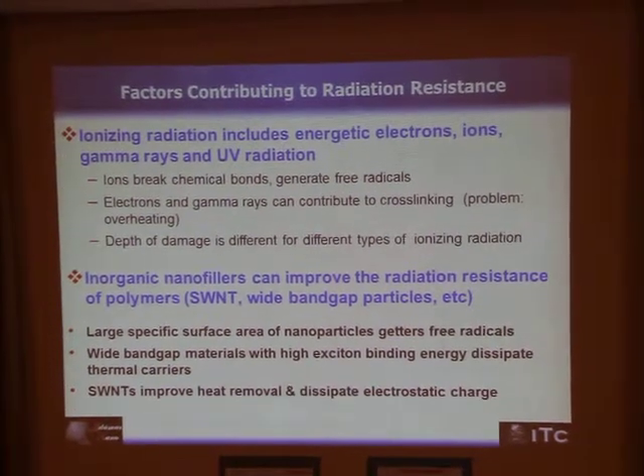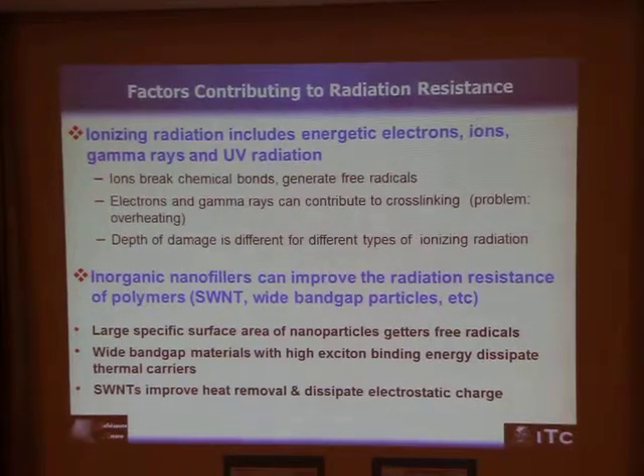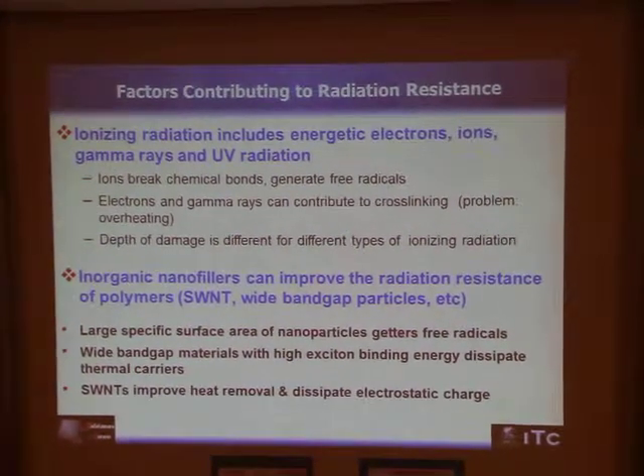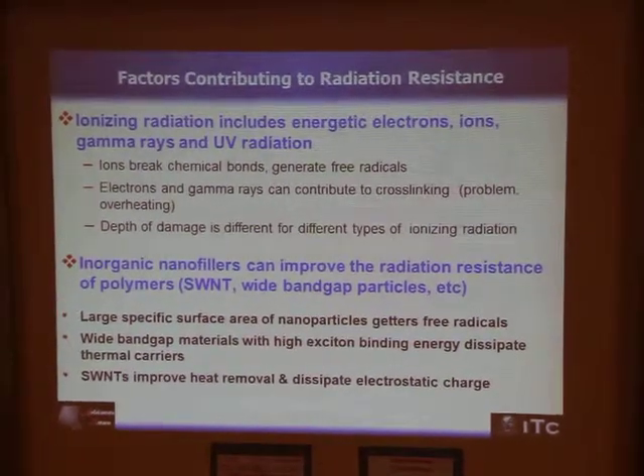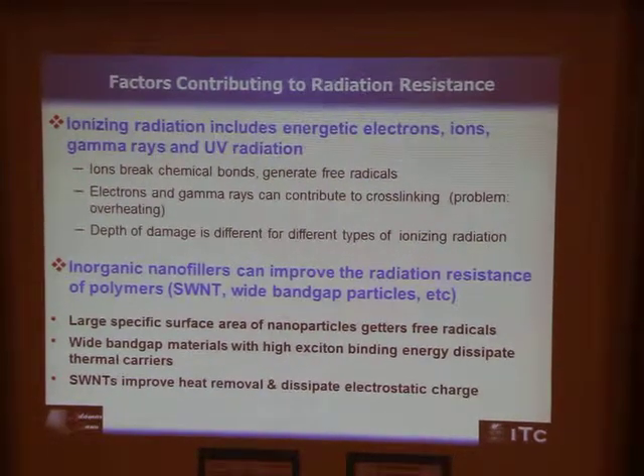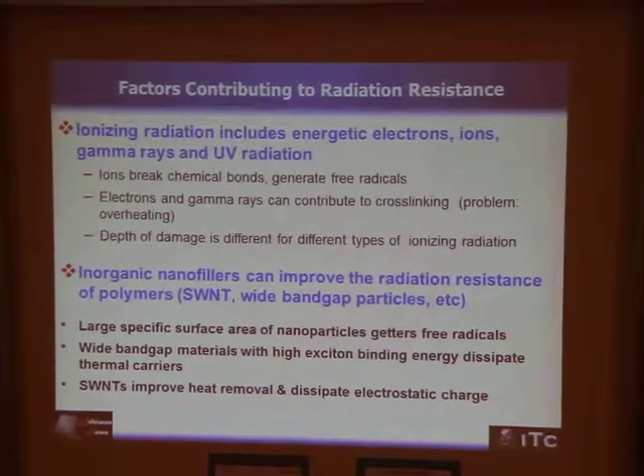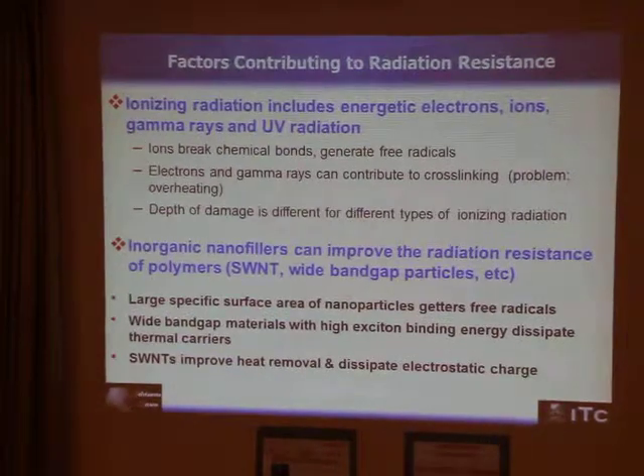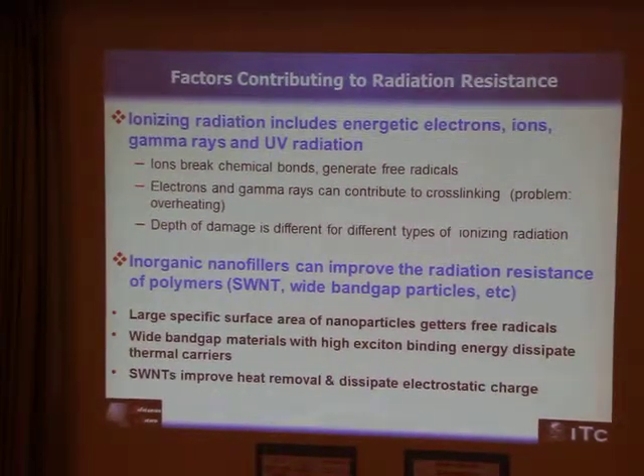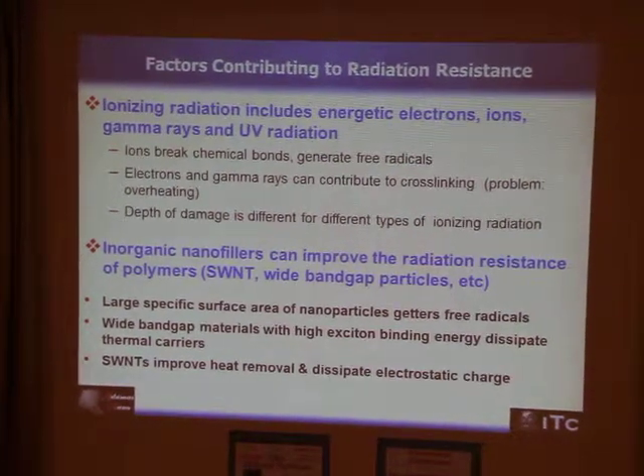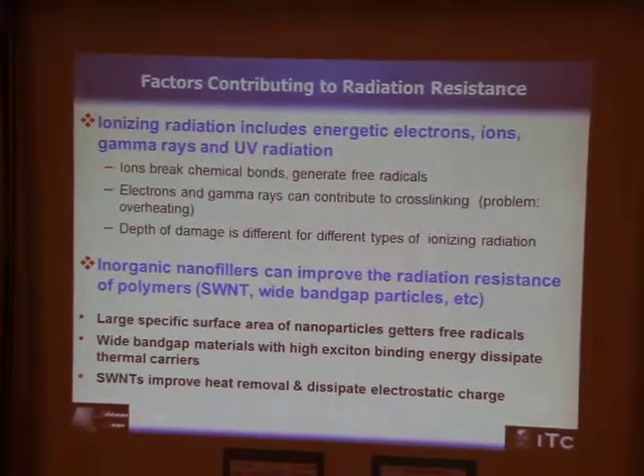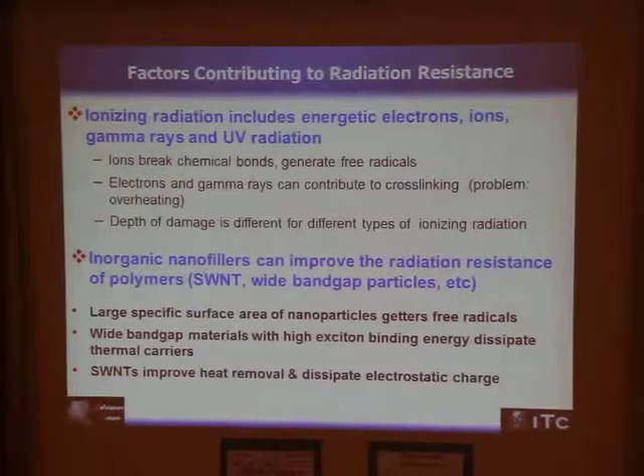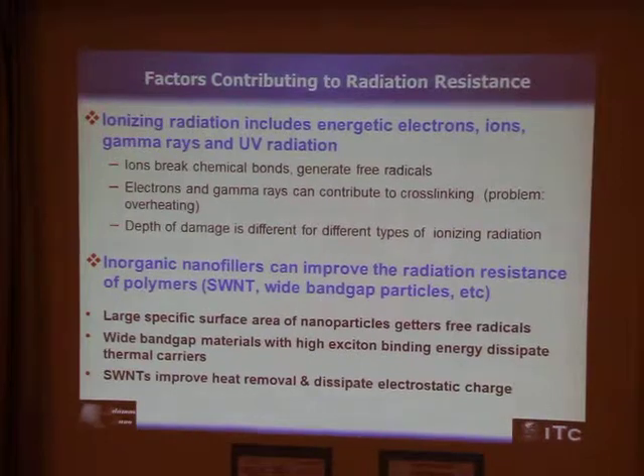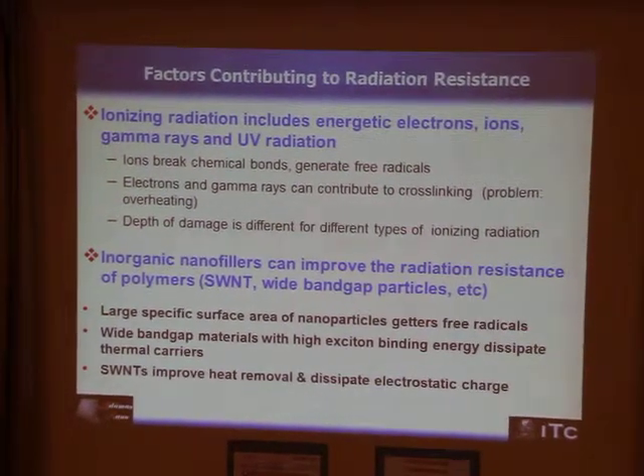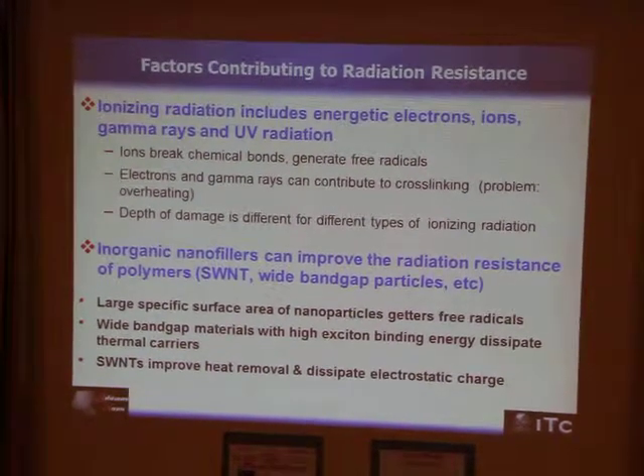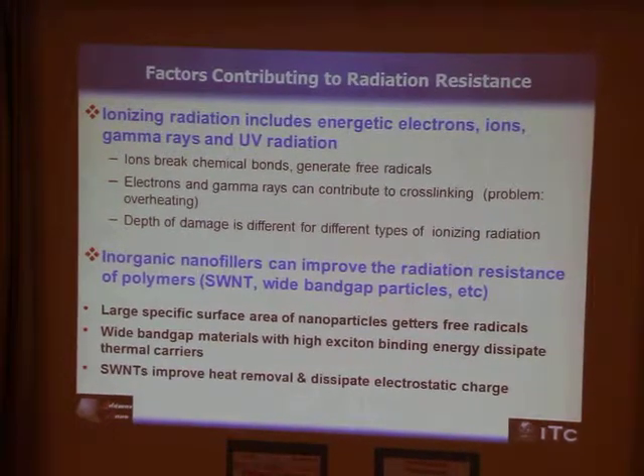So in general, ionizing radiation includes energetic electrons, ions, gamma rays, and UV radiation. Energetic ions break chemical bonds and generate free radicals. Electrons and gamma rays, up to some extent, can contribute to cross-linking, which is a positive event. For all types of irradiation, overheating is a big problem, however, even for electrons and gamma rays in cross-linking mode of operation. And it's also necessary to remember that the depth of damage is different for different types of ionizing radiation. For example, protons can penetrate to 100 microns at MeV energy range, while MeV electrons can penetrate to several millimeter depths in polymers.